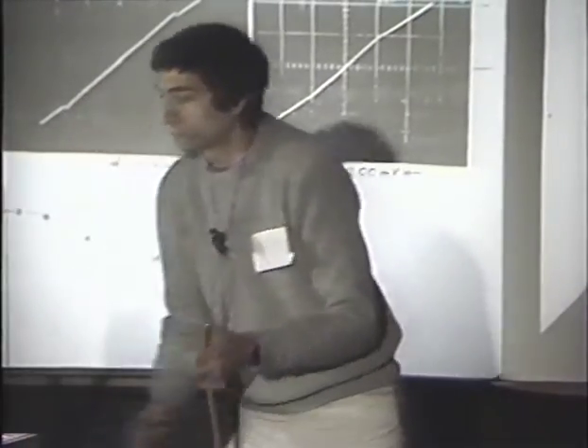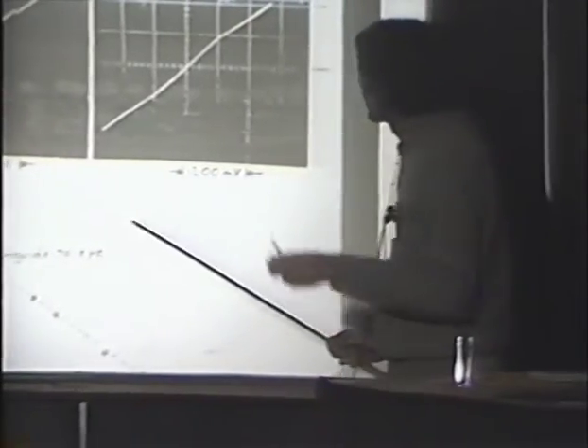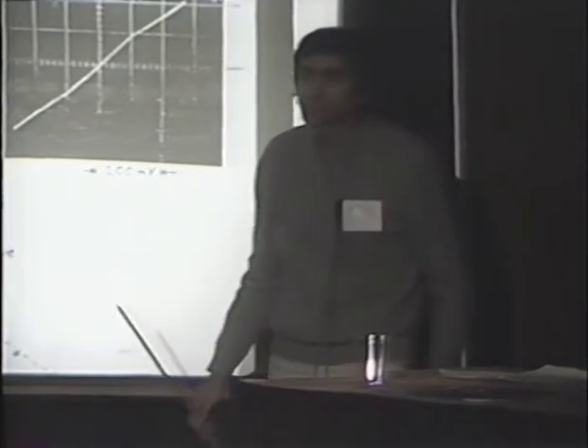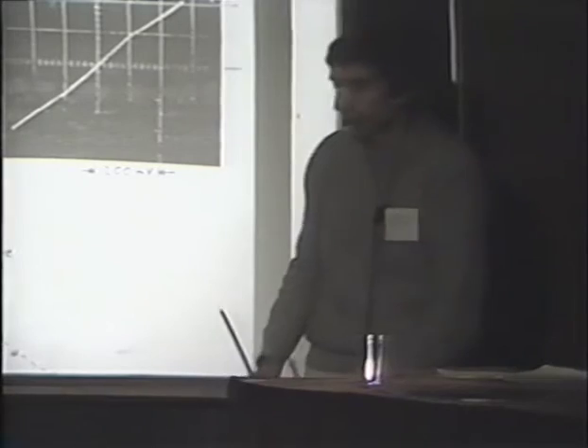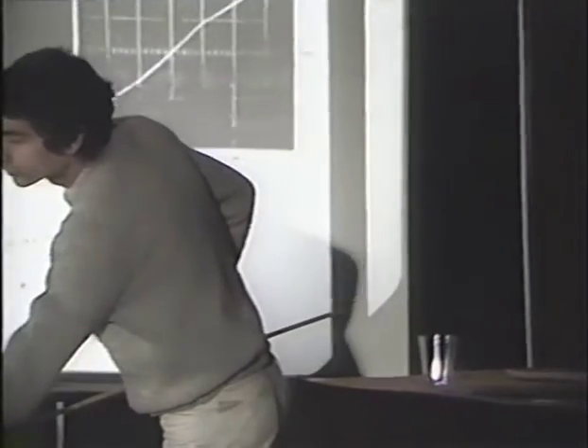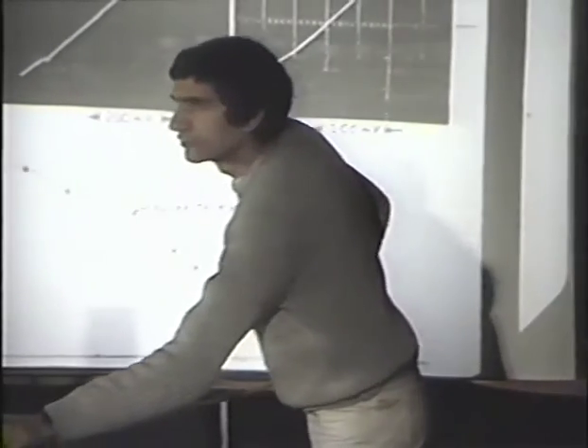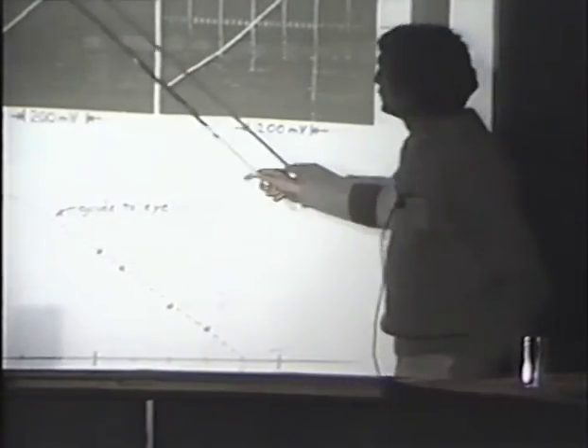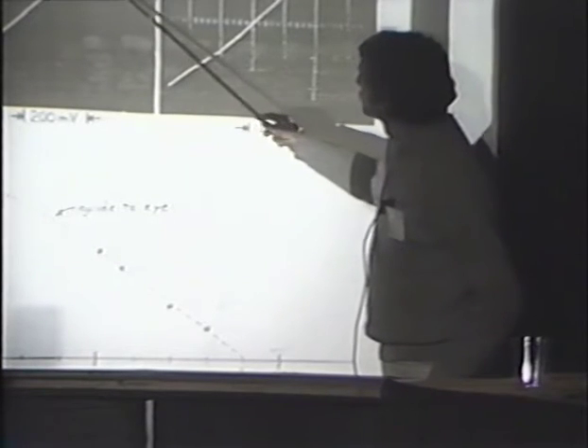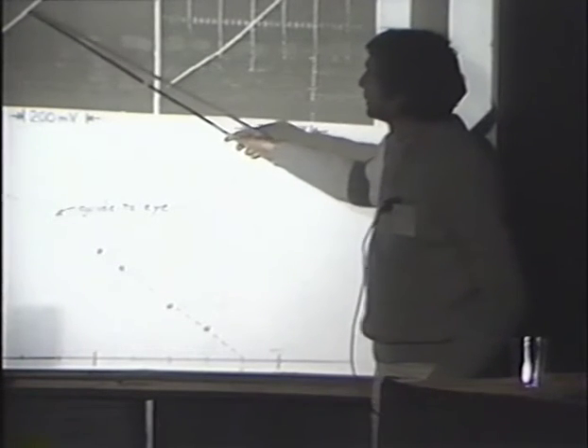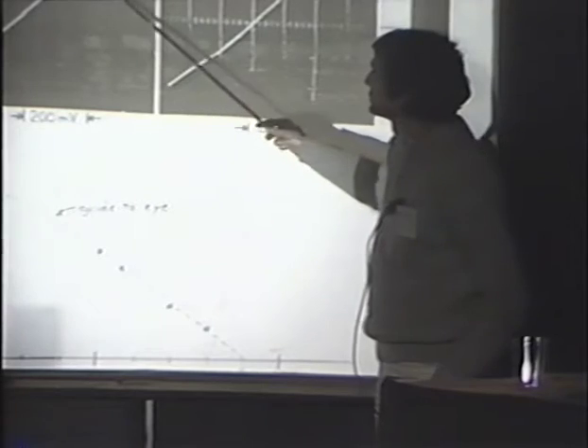We've also looked at the temperature dependence. The typical junctions that we get go from 10 nanoamps to 1 microamp. And the IV characteristics just wash out at 6 to 10 Kelvin, and we have no idea why that's happening at this point. For the large critical current junctions, we've seen several of them, but they're sort of uncommon. At about a milliamp, we see an IV characteristic like this with some sort of structure here. Presumably, it's some contact resistance in the junction.